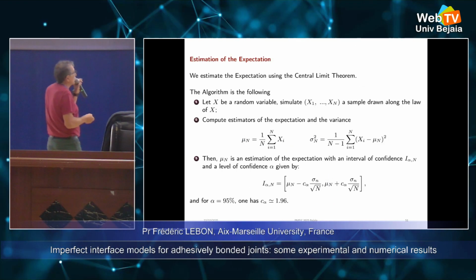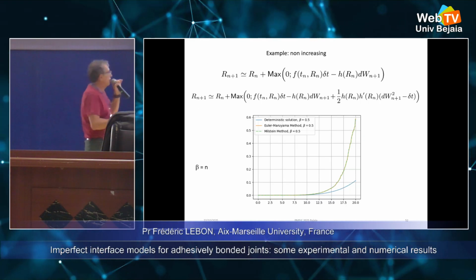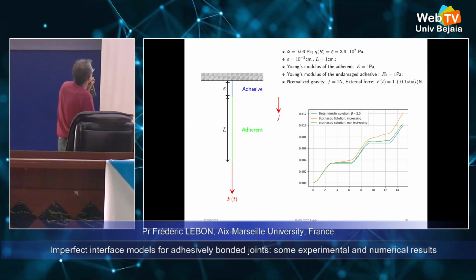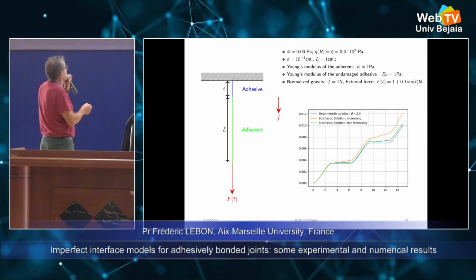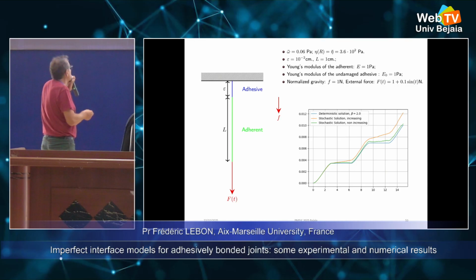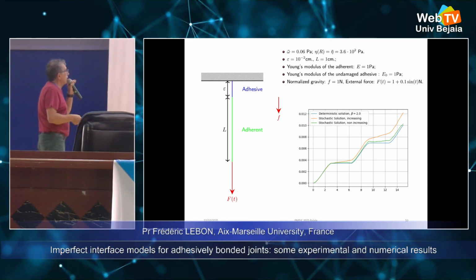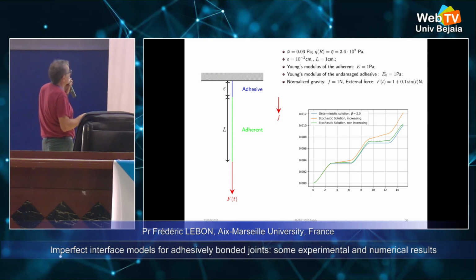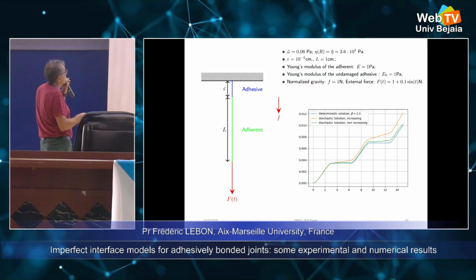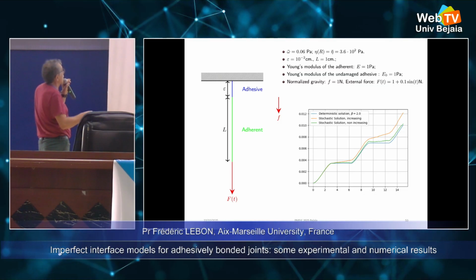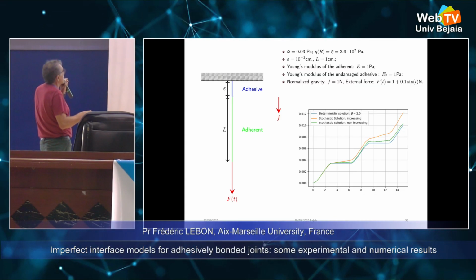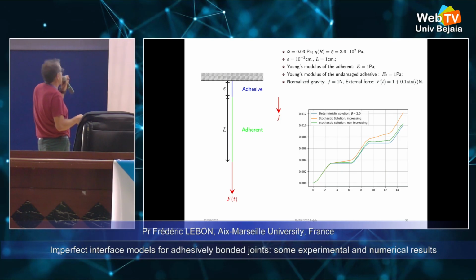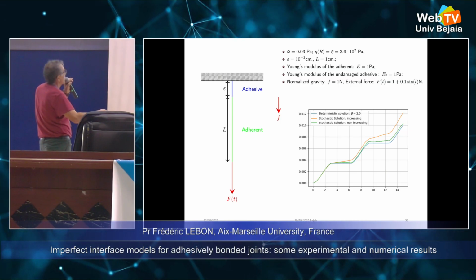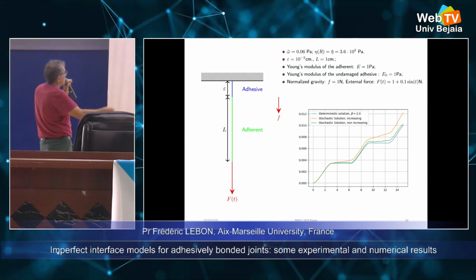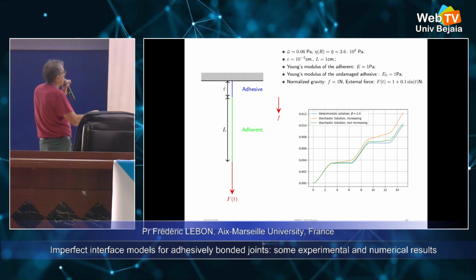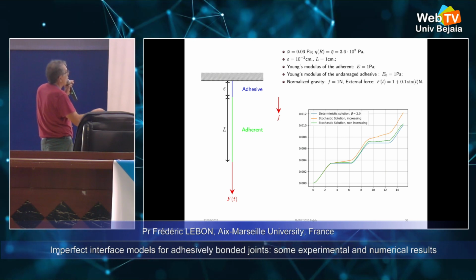I won't show you how it is possible to solve the problem. It's quite technical, but we treat this kind of problem in 1D. We have here the adhesive, with its thickness, and the length is the adherent. It is a bar, and there is a loading which depends on time. We can compare the deterministic solution with the two possibilities of a stochastic solution. And we observe that one is more rigid than the other one. So the idea now is to see if it is possible to observe this at the local level, to see if the good stochastic model is the yellow or the green.